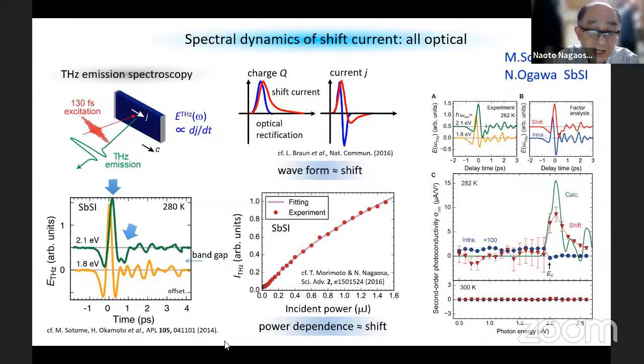This electric field dependence can be shown here experimentally, and this curve is a fitting from our theoretical formula. There is a very nice agreement, so this is considered as one of the pieces of evidence for the shift current mechanism. Also, the first-principles calculation done by Yan Zhang is quite consistent with the experimental observation. So for this ferroelectric semiconductor, this shift current mechanism seems to be definitely acting.